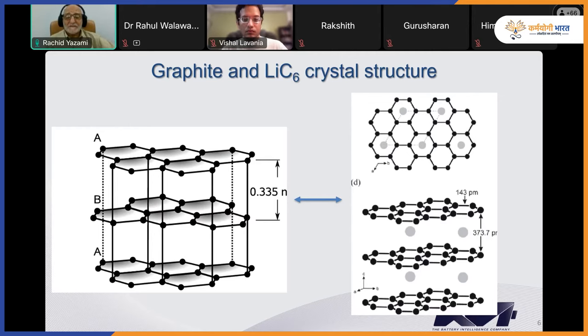So when lithium is intercalated between the graphene layers, there is a volumetric expansion of about 10%. So we are going from, say, 3.35 angstrom in graphite to 3.7 something angstrom. So there's about a 10% increase in volume, and this is the most important characteristic of graphite, that the volumetric expansion is very small, which enables the battery to operate. Unlike other anode materials like silicon or tin or lead or silver, which can alloy with the lithium, the volumetric expansion can be more than 200%, 300%, which means that these materials cannot be used in a practical battery because of the huge volumetric expansion.